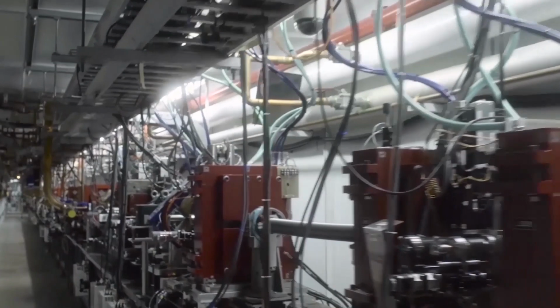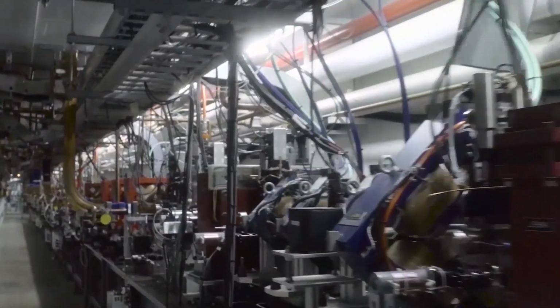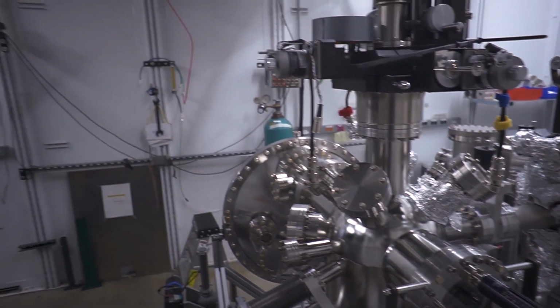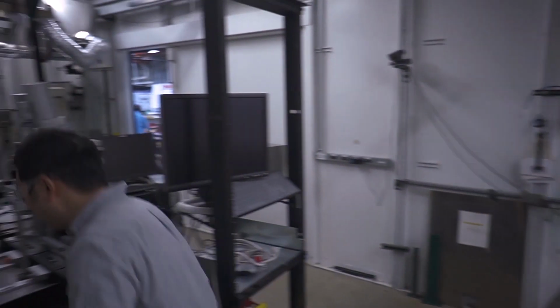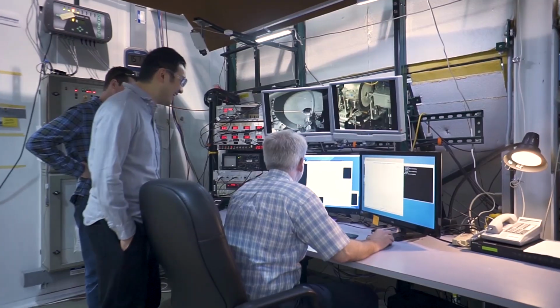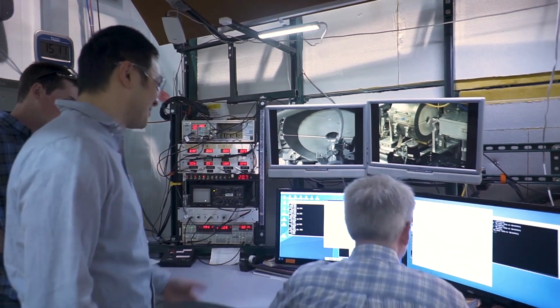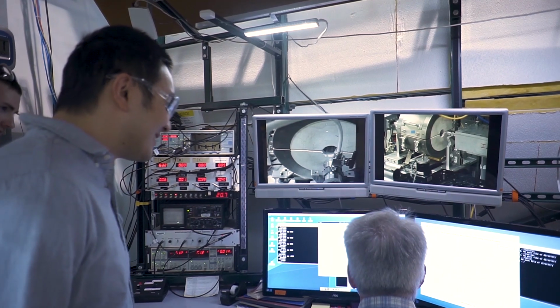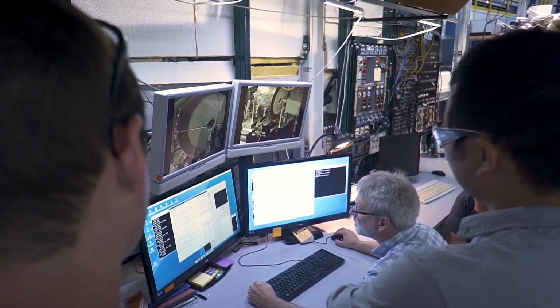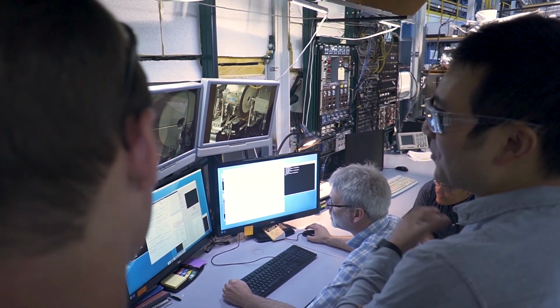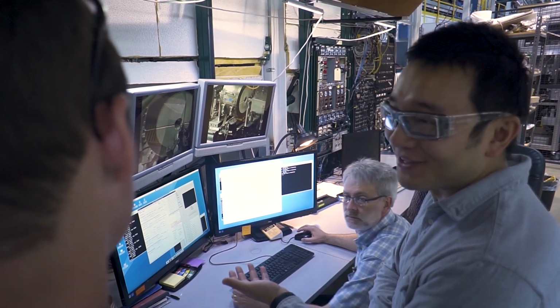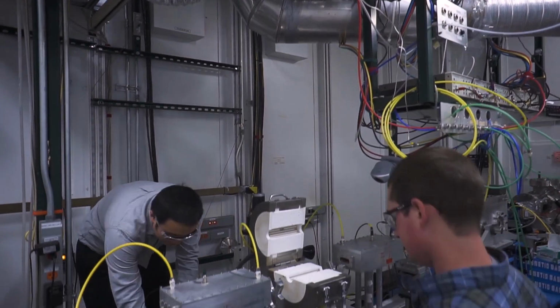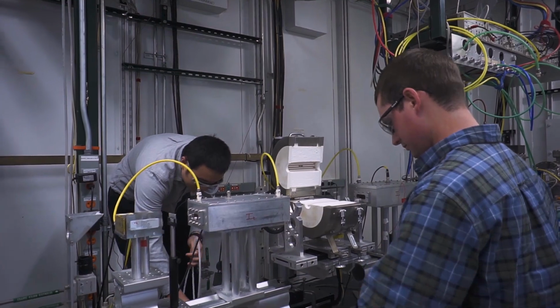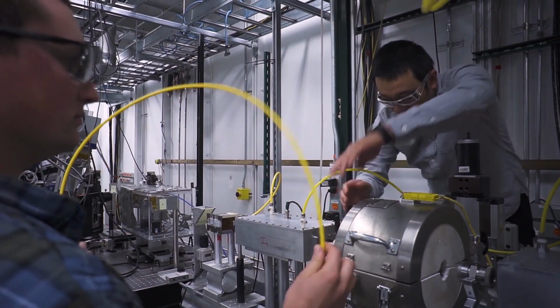We use X-rays to understand the chemical and physical properties of the catalyst. In X-ray spectroscopy, we use 2 techniques: X-ray near-edge spectroscopy and X-ray absorption fine-structure analysis. This provides insight into chemical and physical properties of the catalyst, such as the catalyst oxidation state, the particle size, and the nearest neighbors around the atom of interest. But we also do in-situ studies, and this gives the real, true picture of how the catalyst is performing.